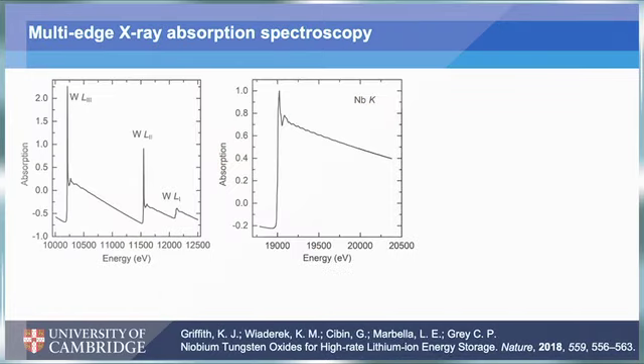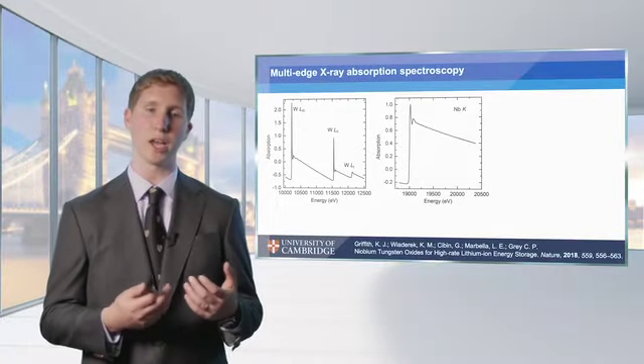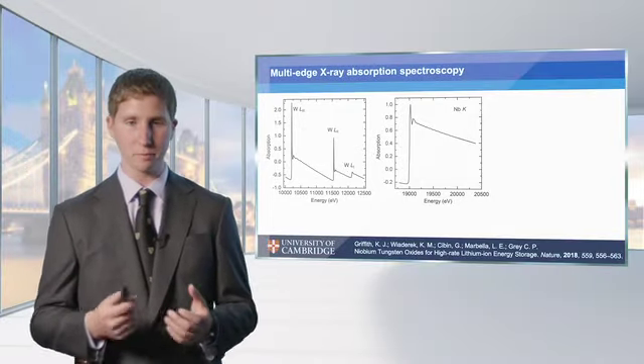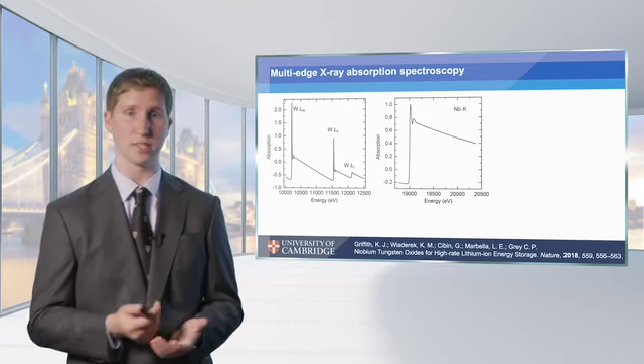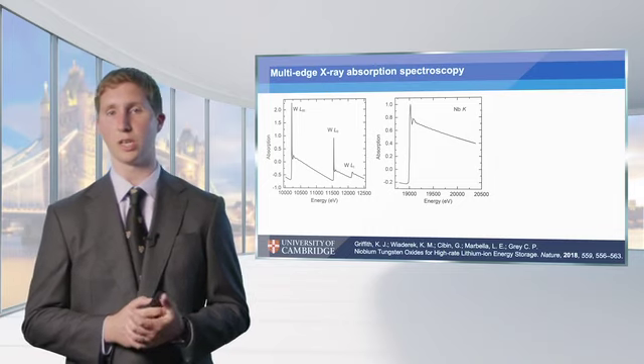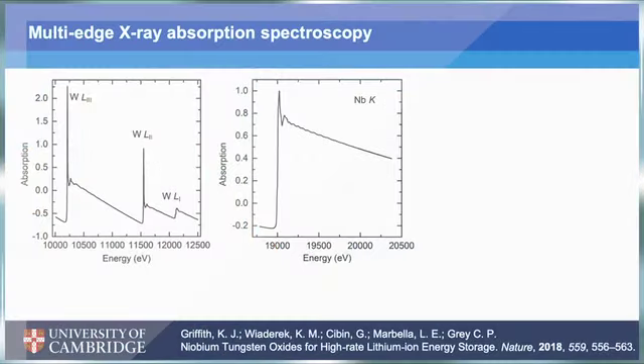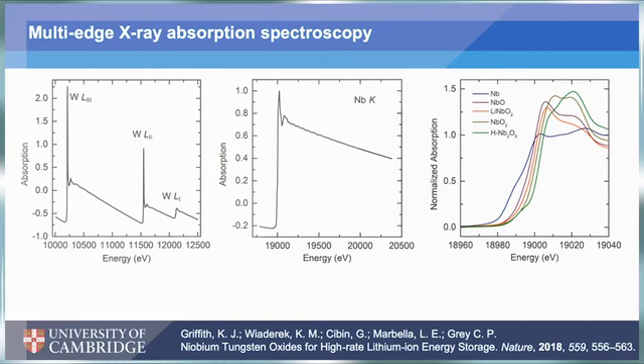And so X-ray absorption spectroscopy is a local structure technique where we're actually able to individually look at, say, the tungsten or the niobium in our materials and try and learn about how the chemistry, so the oxidation state of these, is evolving as a function of state of charge, and also look at how the local structure, the local symmetry, is evolving as a state of charge. And so we did this individually, and in this plot on the right, you can see that we should expect a shift in the absorption edge as a function of the oxidation state. So from niobium 5+ in Nb2O5 all the way to niobium 0 in niobium metal, we see about a 20 eV shift in where that absorption occurs.